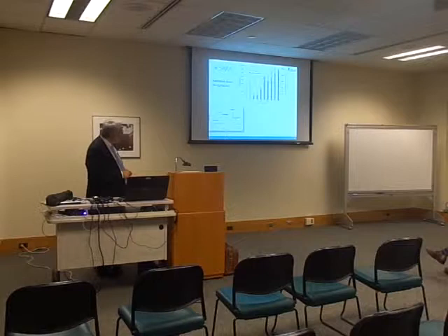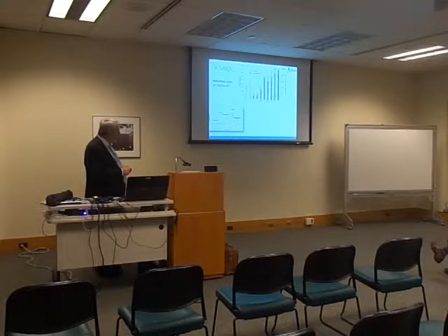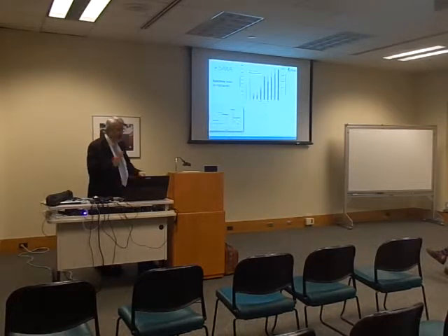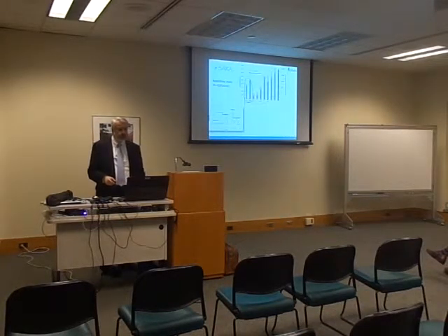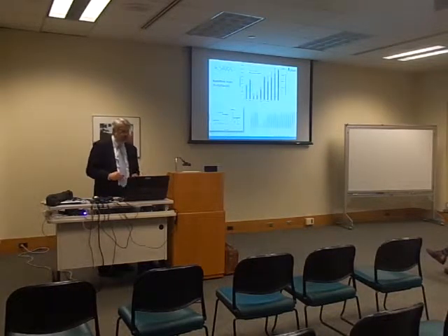Why are they softer? Because the complex modulus says they are softer. You see, the complex modulus of those is lower than the complex modulus of the H bitumens. And a chemical indication that the chemistry can control is to say, okay, then I'm going to choose rejuvenators with low asphaltene index because I know that they will have low complex modulus. We had two exceptions where a substance had a high asphaltene index but a low complex modulus. And I'll get back to them later today.